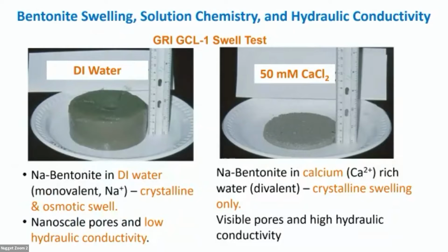And just to illustrate this, I did a couple of examples here. I took the bentonite that would be in a GCL, again, about 4 kilograms per meter square granular bentonite, took that mass per area out, put it inside a Proctor mold, 100 millimeter diameter mold, and it's about 6 millimeters thick dry, so a thin layer at the bottom. And then we pour the solution that's going to be hydrating it on top of that liquid. And we watch it swell. This is an old swell test developed by the Geosynthetic Research Institute about 25 years ago, but a really illustrative test.